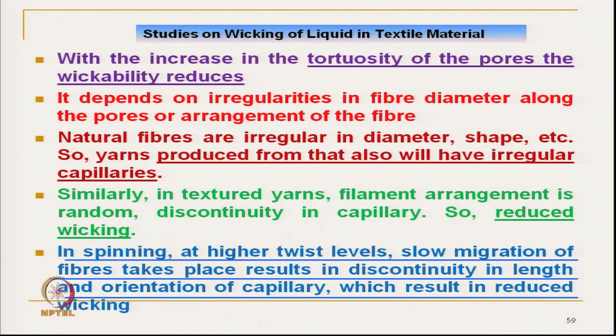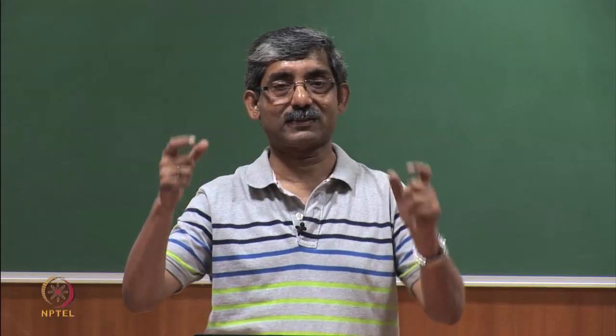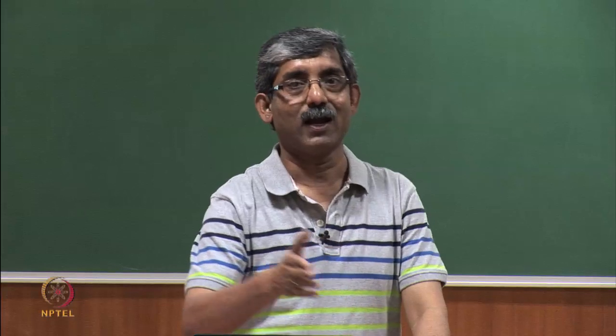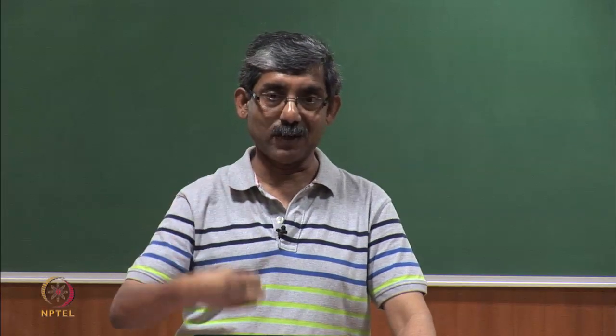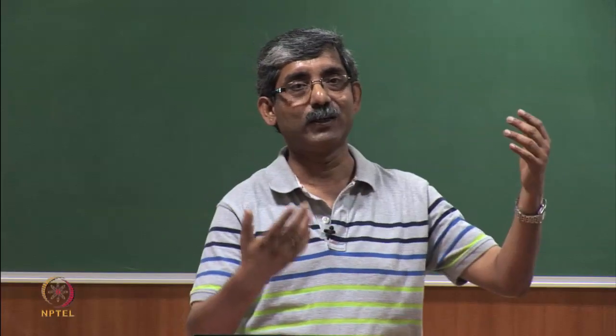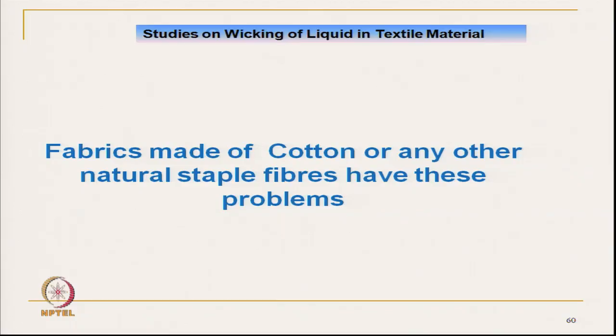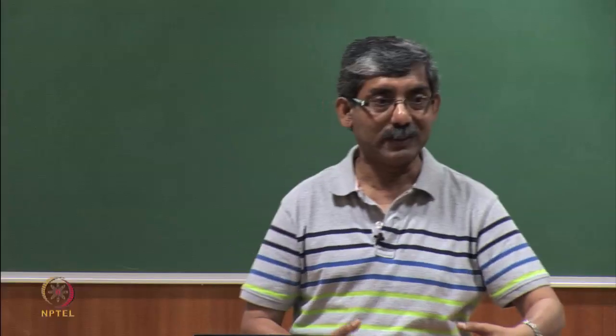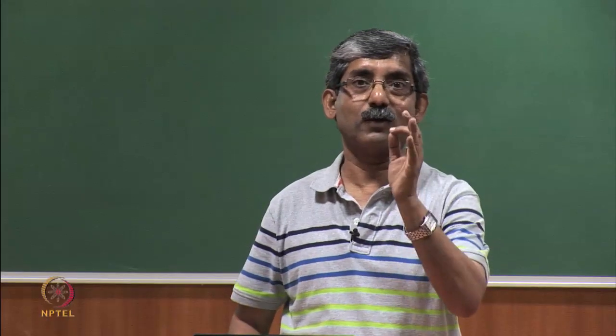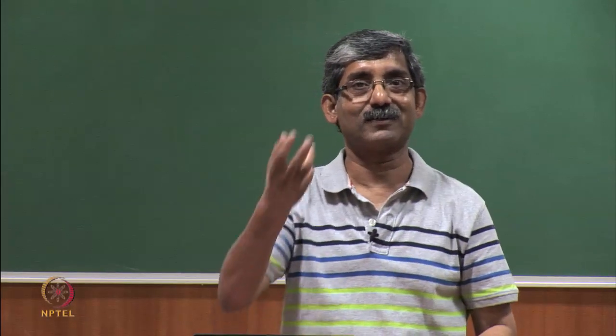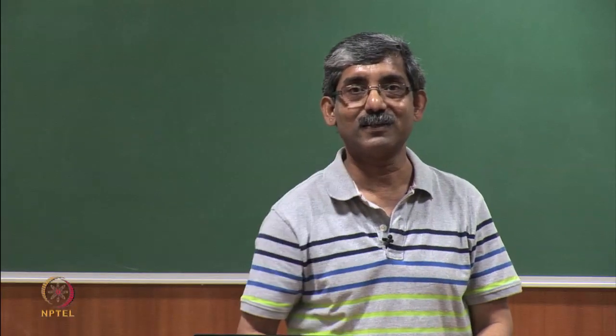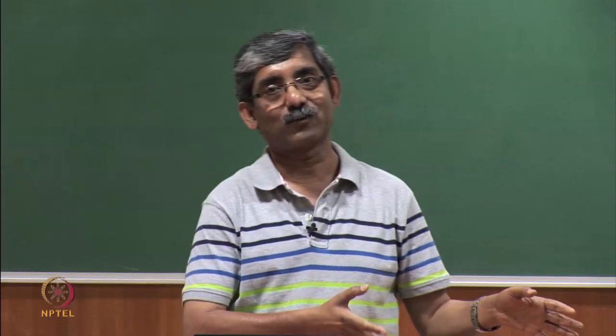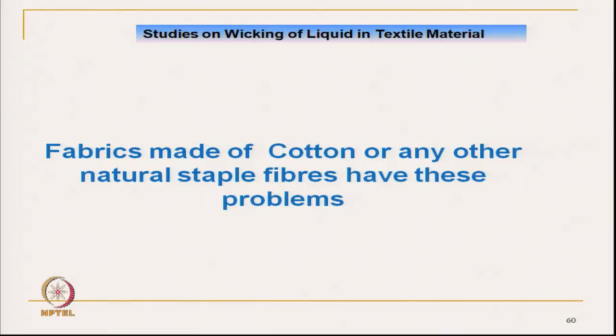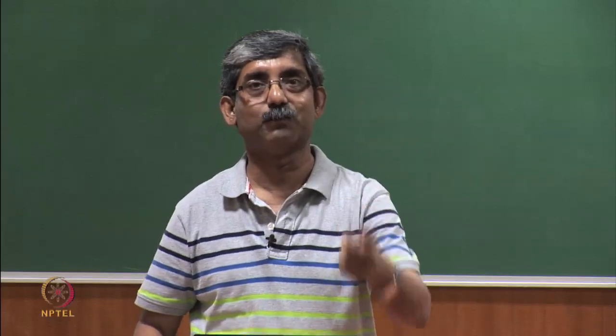If we take the same polyester, one in filament form and another in staple form, staple polyester will have much lower wicking than the filament. That is why fabric made of cotton or any other natural fiber has this problem. The wicking rate will be less, although cotton has two problems. One is that it is hydrophilic in nature, it retains the moisture, and also the wicking is less due to the shape of the pores.